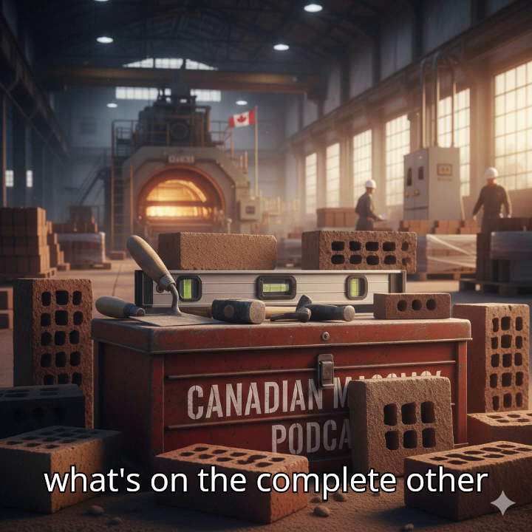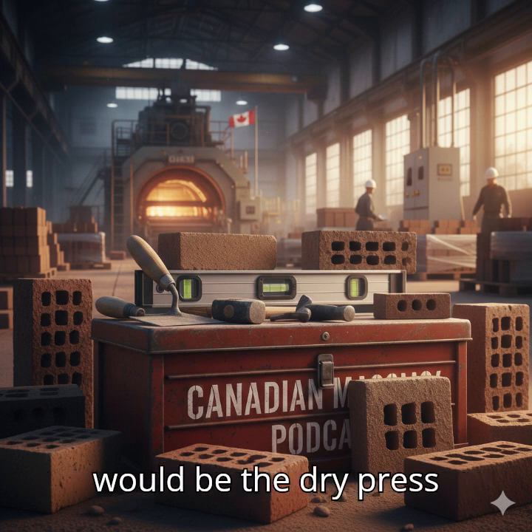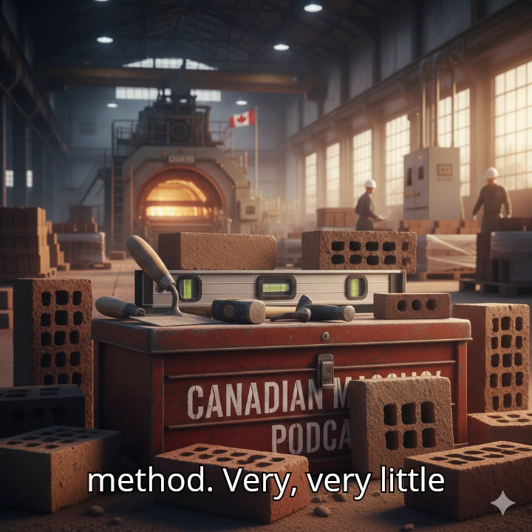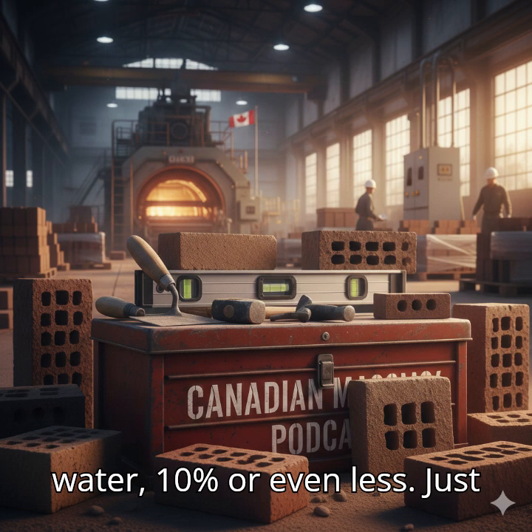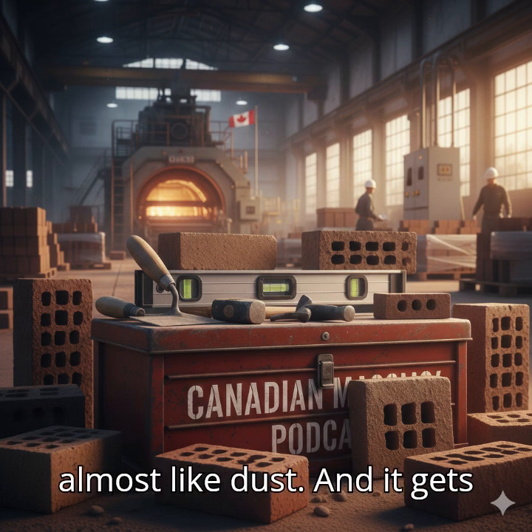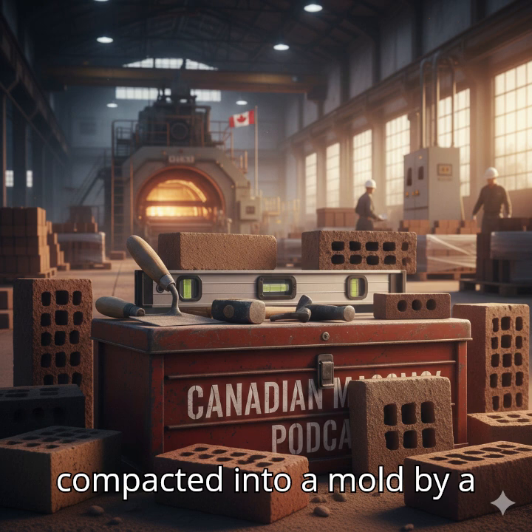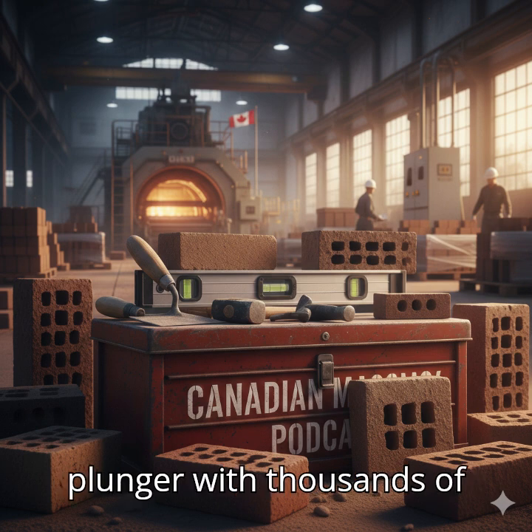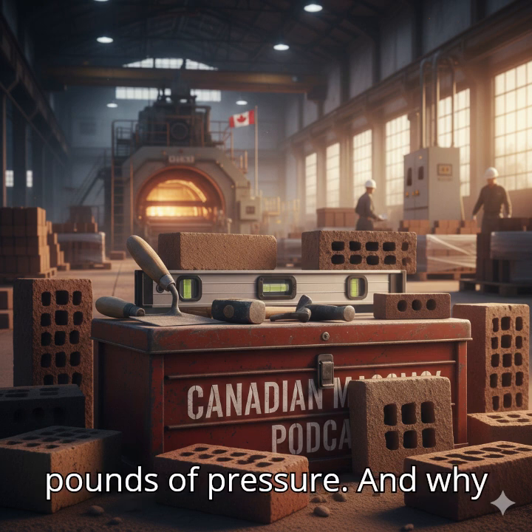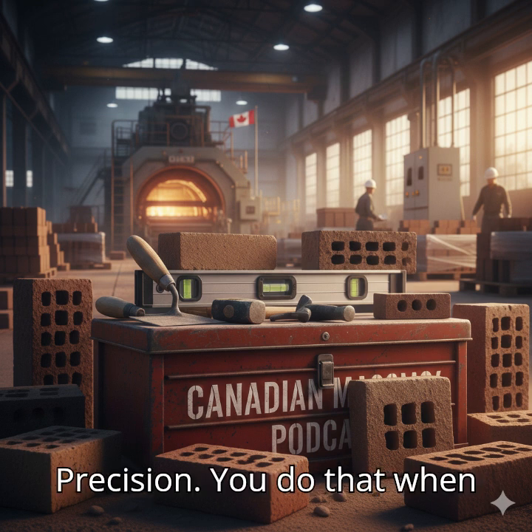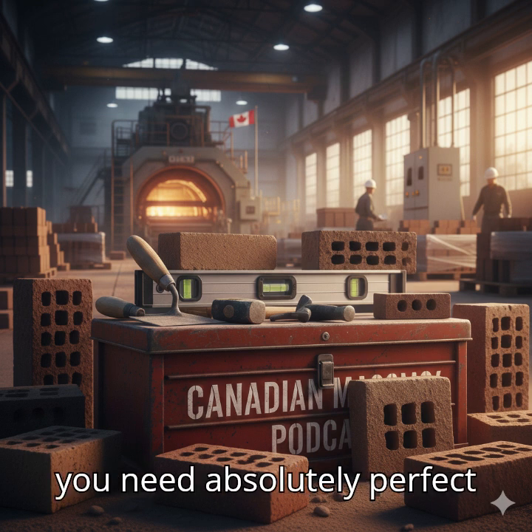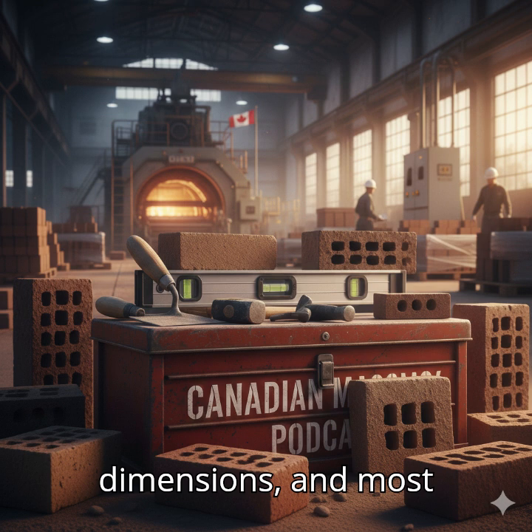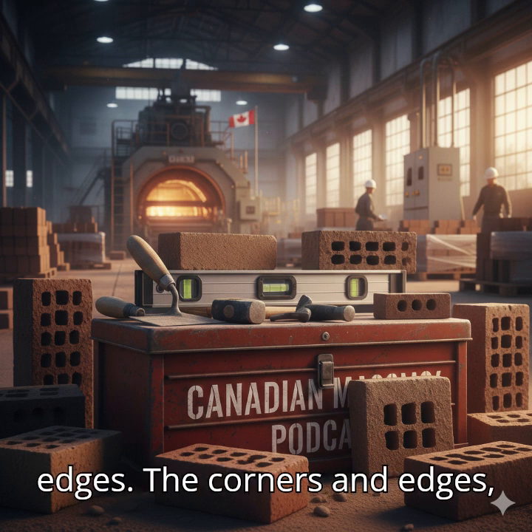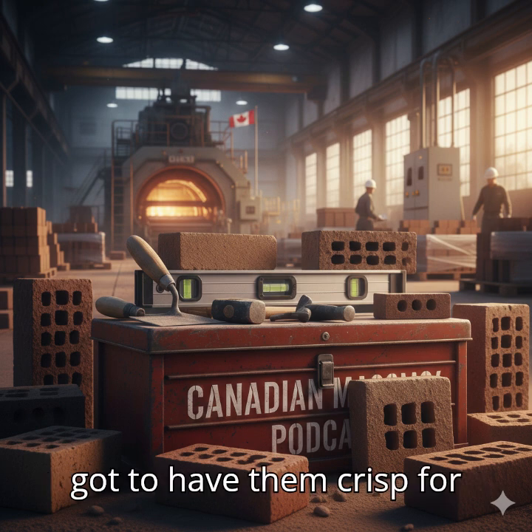So what's on the complete other end of the spectrum? That would be the dry press method. Very, very little water, 10% or even less. Just barely damp. It's almost like dust. And it gets compacted into a mold by a plunger with thousands of pounds of pressure. And why would you use that method? Precision. You do that when you need absolutely perfect dimensions and, most importantly, super sharp arrises. The corners and edges, got to have them crisp for certain designs.